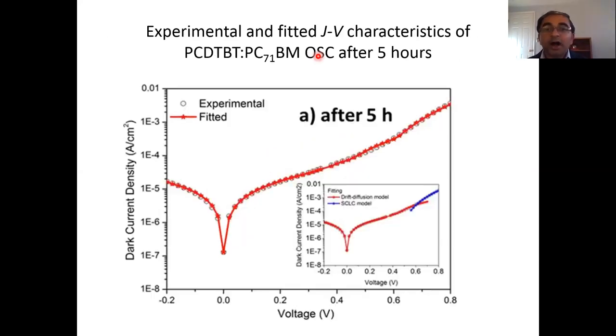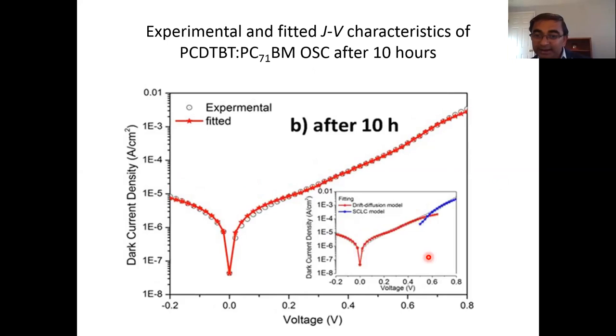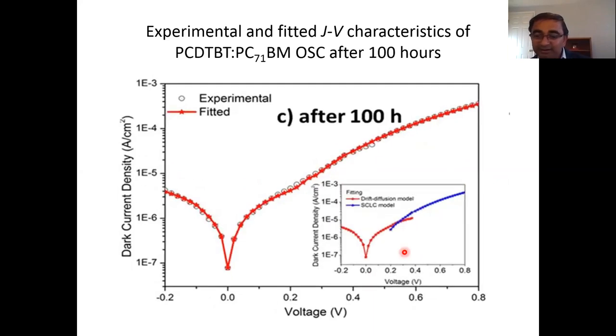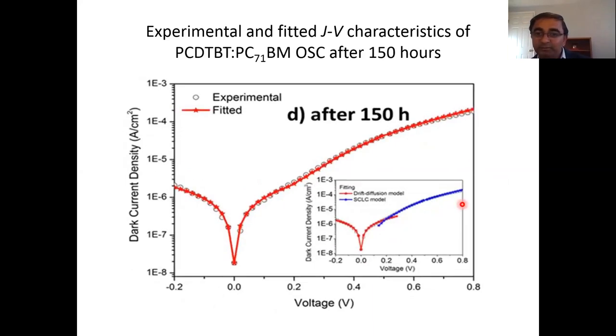Now, after 5 hours, you can see from here, you cannot fit the graph only with the help of the drift diffusion model. You have to take another model also, and this is the space charge limited current model. And you can see from here, there's a transition from the drift diffusion model to the space charge limited model after a particular voltage. After 10 hours, you can see that the area of space charge limited current modeling is increased. After 100 hours, you can see again it is increased, and after 150 hours.